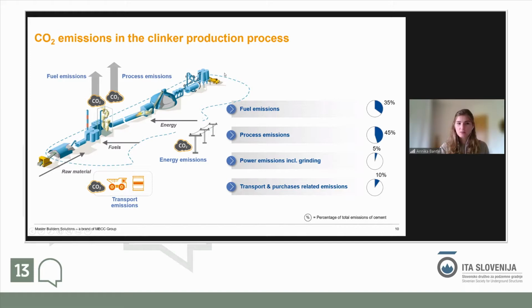And that's why I brought you this picture of the process, just a very basic description here. You have the raw material flow, you have the quarry from the site, then you crush the limestone, then you mix it, you dry it, you grind it. This is all taking place here. Then you have your fuels that you use to heat up the rotary kiln. And this is really where it gets interesting, because the rotary kiln is the part where we have the highest emission within the production process, which you see on the right-hand side.